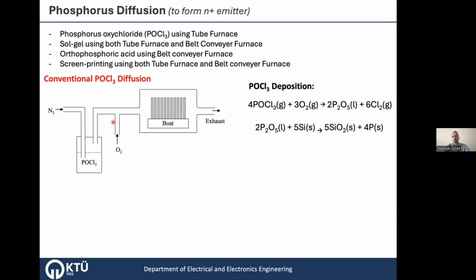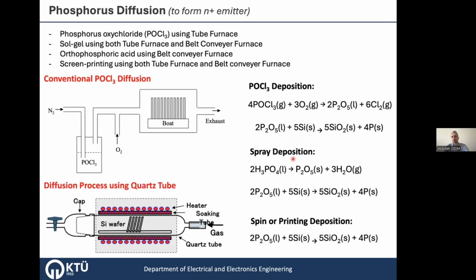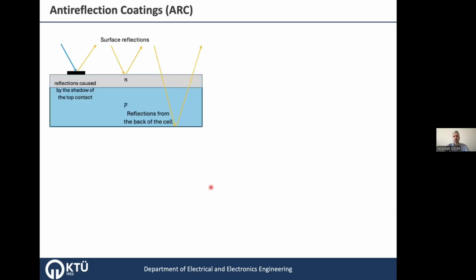After the deposition is completed, we halt the N2 gas and introduce oxygen to the tank, and the reaction produces phosphorus pentoxide, which reacts with silicon and diffuses into the silicon wafer and forms the N layer. The other processes like spray deposition or spin printing deposition are similar, but in that case, you just spin, spray, or print the phosphorus source on the surface of the wafer, and then with the appropriate thermal profile, you can directly make the thermal process and have the N-type formation on the front surface. So that's the N plus emitter formation. And next one is the anti-reflection coating.